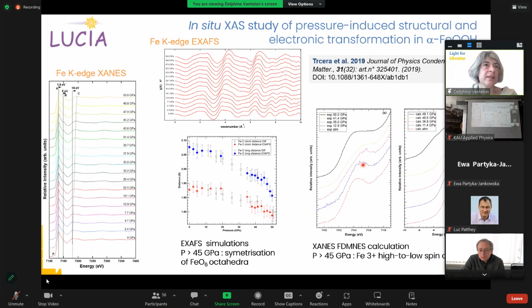Then I show you two examples of in situ modification of materials under constraint. Here is under high pressure in an anvil, in a diamond anvil cell that is dedicated to LUCIA, as it allows to use thin diamond to allow the transmission. And so here we can reach 50 gigapascal. And here you can see that with the EXAFS, they could see that above 45 gigapascal, they observe the symmetrization